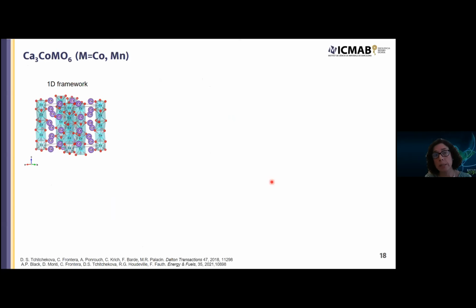Then when looking at the other group of compounds, calcium transition metal oxides, we were interested in this compound, which is a derivative of the hexagonal perovskite, and its crystal structure is made of columns of alternating cobalt octahedra and prismatic coordination, which are sharing faces, or in some cases one can have also manganese, and there is calcium between these columns. Our idea was that maybe this crystal structure would favor calcium mobility through these columns.